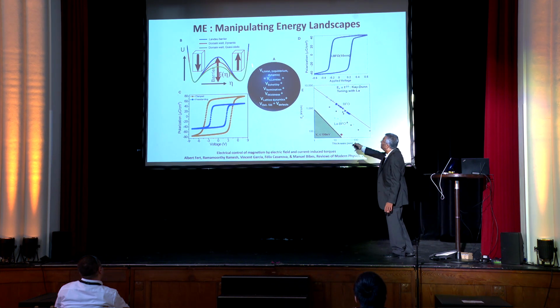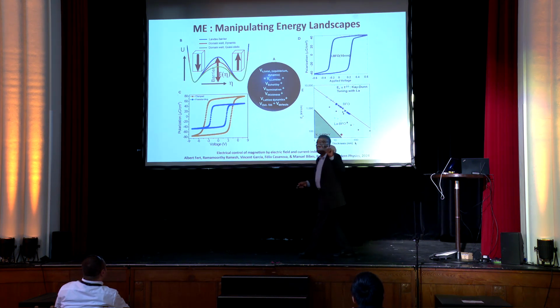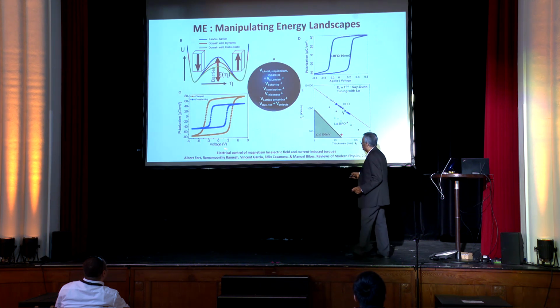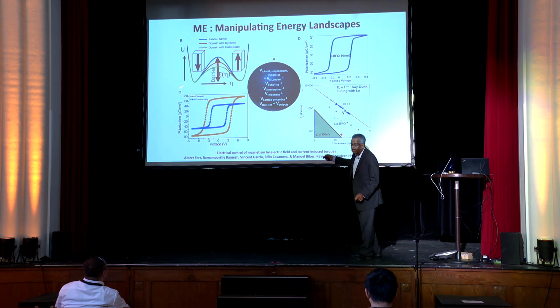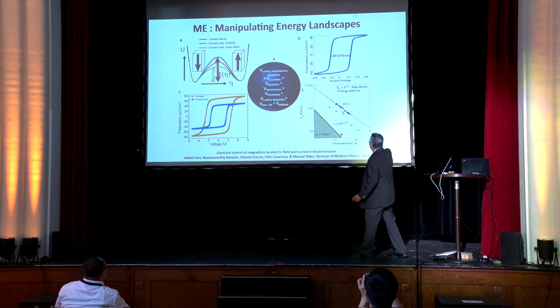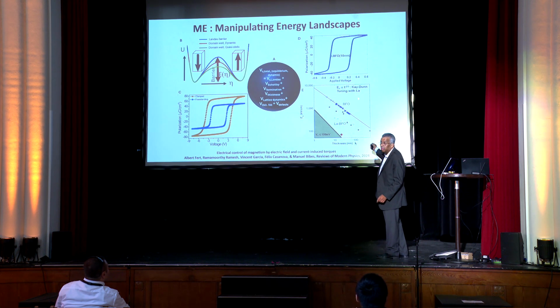We have to be able to manipulate the double well structure. You have to really pay attention to every atom. In the case of electric field, we're looking at very small thicknesses, maybe 3 to 5 nanometers. How do you make perfect materials? How do you overcome mechanics of the ferroelectric? We know that we can get to about 200 millivolt switching, but we need to get to much lower voltages.